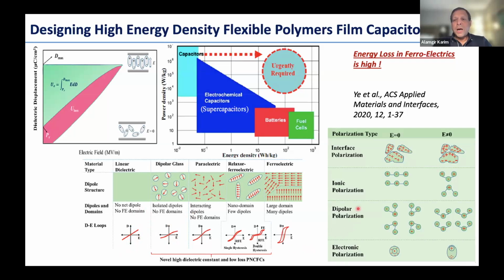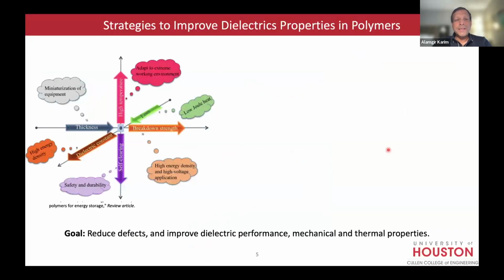The important point is, how is the energy stored? So there are all levels of energy storage. Electric polarization: dipoles can get polarized if there are dipoles in the system by the applied field. When you're charged, you align the dipoles. You align ionic more material. For example, ionic liquid could be oriented. These days, they're making polymerized ionic liquid, which is very cool. So that's a very good candidate, I would say. But even interfaces can hold charge because of dielectric mismatch between two materials at the interface. I'll show an example of this that we looked at, and we think there's actually much potential for this as well.